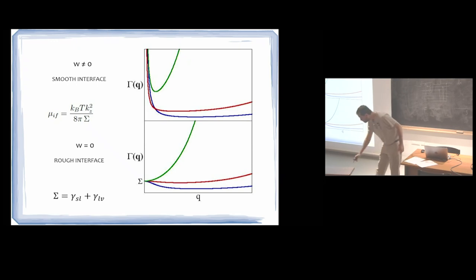Perhaps you could look at small wavelengths and see some bumpiness. But for the whole bench, it's flat. So you cannot bend it. So your surface tension becomes infinite. So the surface tension of ordinary smooth solids is infinite for large-scale deformation. If you are a fluid interface, you can deform always, very easily. And the cost of deforming is just a finite surface tension. Okay?